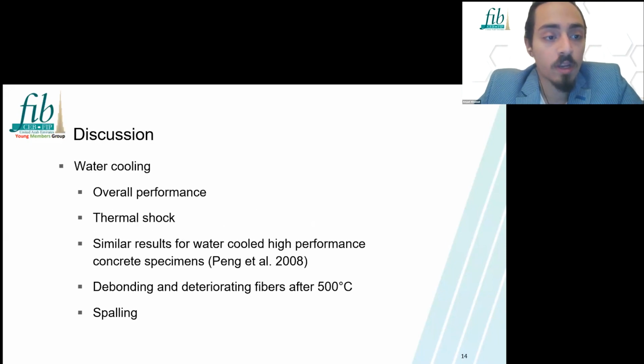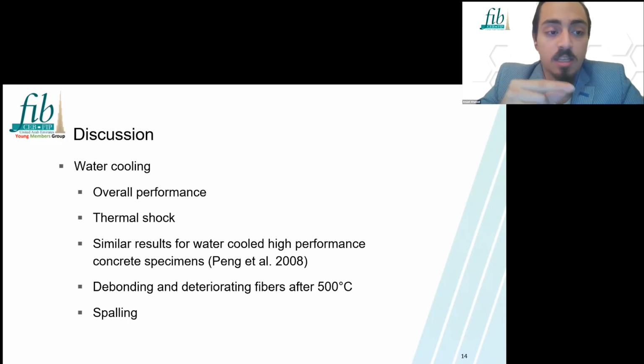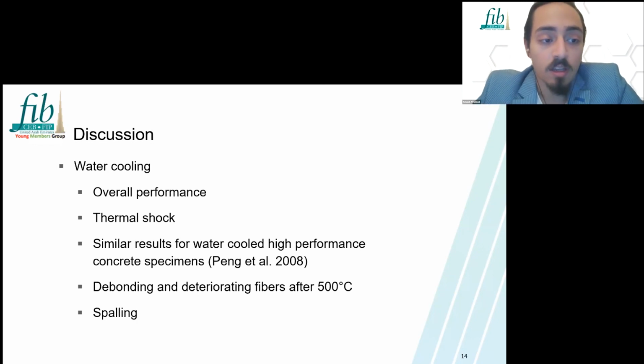Now on to water cooling. For this type of cooling, the concrete undergoes a direct decrease in strength, as you saw in figure 7, which is expected since here we have something called a thermal shock. This thermal shock creates a difference in stresses between the outer core and the inner core of the concrete. And these induced stresses will damage the concrete and reduce its overall strength. This behavior was found in several studies, more notably in one regarding HSC, in which there was no increase in strength at all, just like we had.